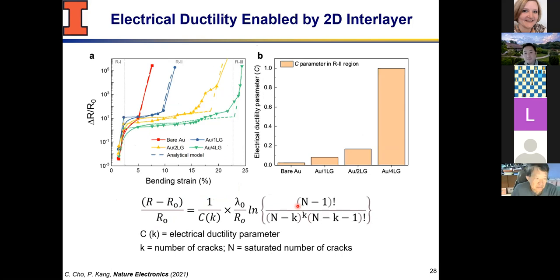We attempted to understand this a little better. And this was a model that I think was some sort of a carbon nanotube composite type of model developed. So there are crack generations as we increase strain, but at the same time, there are continuous bridging that are enabled by these nanostructures that are embedded in the elastomeric or polymer substrate. And our measurement fits really, really well with this type of model, which also suggests that the crack bridging that I talked about is a part of what we see as a result of this electrical ductility, or this enhanced stable resistance.